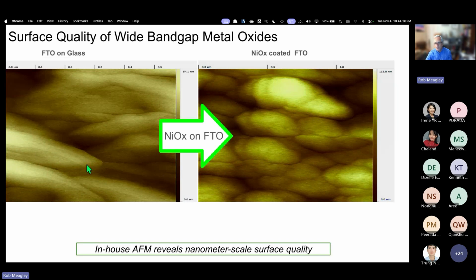Here we have a zoom in of those two same samples. Here we can see crystal facets in the fluorine-doped tin oxide down to just about a nanometer. This nice crisp line is a ridge. This nice crisp line here is a trough, and then here is another ridge. And if we look over at the nickel oxide coating, there's just a slight suggestion of the trough. We can see the junction at the edge of the crystal face here, this facet. But for the most part, a lot of the most concerning sharp topography is covered, and we believe that this is a contiguous coating.